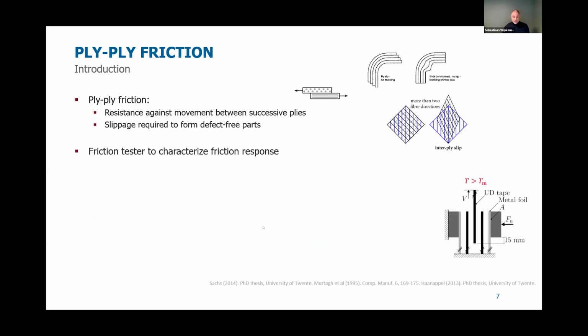In the past, we have developed a friction tester where we really try to manage the pressure distribution and temperature profile, and measure the forces required to pull one layer out from between two other layers, or between metal substrates. So we can also measure the tool-ply friction with this device. If you look at the bottom of this slide, you see a small reference, and in the reference we also see Haanappel, and Sebastiaan was in fact the first PhD student to graduate with the TPRC.